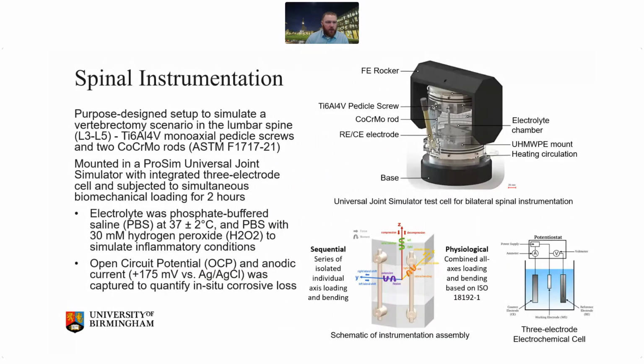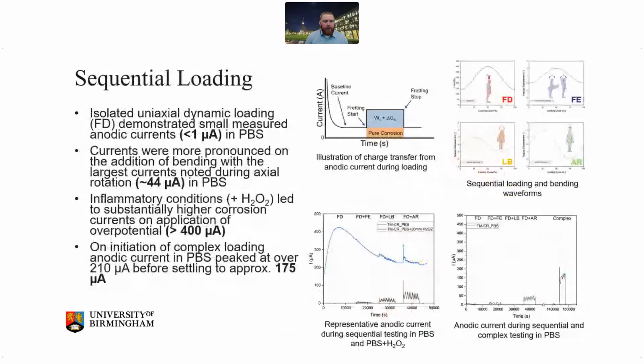So this was some work that we did around bilateral spinal instrumentation on the universal joint simulator. So again, subjecting these devices to what is basically standardized testing in uniaxial loading versus applying actual complex biomechanics to what you would then see as a degradation response. So what we found is essentially, yeah, this was a set of testing where we sequentially ran through different profiles by introducing different axes of rotation. And then once you get to the point where you're actually simulating the complex biomechanics, you see a significant increase in the amount of corrosive degradation there.